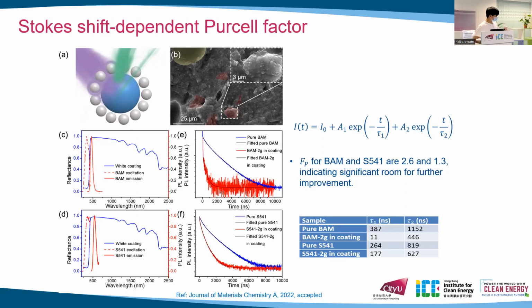After adding these two phosphors into the coating, we can find PL lifetime reduction for both phosphors. And we fit this PL lifetime using a biexponential function. We can find that both non-radiative and radiative lifetimes were reduced, and the Purcell factor can be obtained by the ratio of the radiative lifetime before and after the phosphor was added into the coating. And then we obtained a Purcell factor of 2.6 for BAM and 1.3 for S541. This is not high because in an ideal optical cavity, the Purcell factor can be several orders higher. But in such a random system, this value may be pretty good.